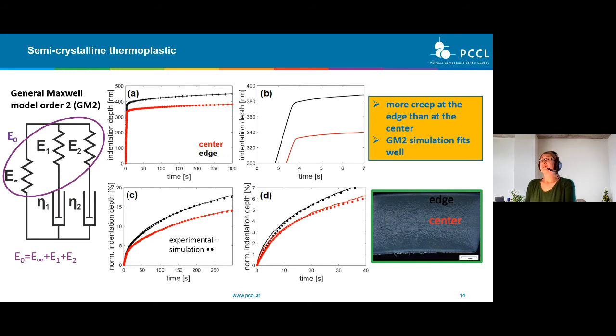So next, I would like to show you first of all the data modeling, or the creep modeling, of the POM investigations. I have here the indentation depth over time curves, so the creep curves. And in red, I have a measurement and a simulation. The simulation are the dots from the center of the sample. And in black, we have measurements from the edge of the sample. What you can see here is that for the edge of the sample, we have a higher indentation depth than at the center of the sample. And also when we normalize the experiments, you can see that we have higher creep at the edge of the sample in contrast to the center of the sample.